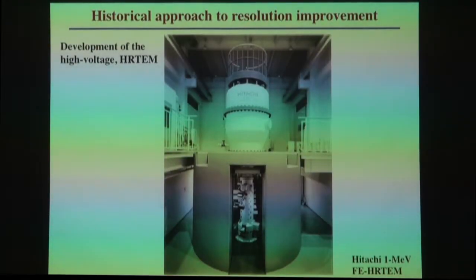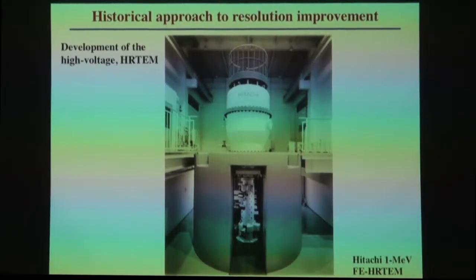How are we going to do better? Historically, you could do better by going to higher voltage, because we all knew back when that the resolution was determined by a product of the spherical aberration coefficient and the wavelength. The only way to do better was to go to shorter wavelengths, which says we had to go to higher voltage. And so here's the Hitachi 1 million volt microscope, again at Tonomura, produced just before the turn of the 21st century.